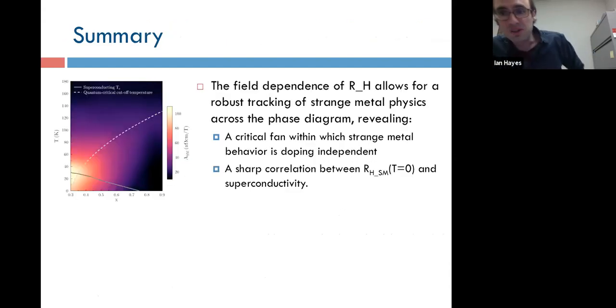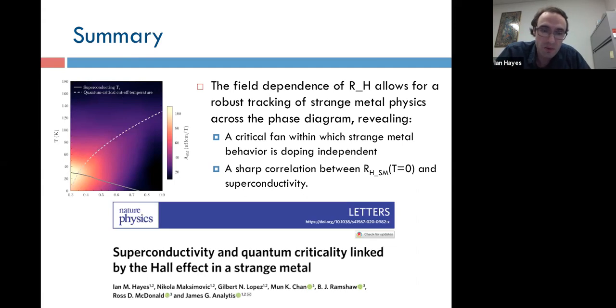All right, so with those admittedly very broad statements about what I think the implications of these results are, I just want to remind you of the highlights. By looking at the field dependence of RH, you can isolate a fraction of the Hall coefficient that seems to correlate both with superconductivity and to exhibit this intriguing fan-like feature that seems to tie it to the behavior of the antiferromagnetic phase. And if you have further questions, I direct you to the paper we just published, or you can ask them right now. So thank you very much for your attention.